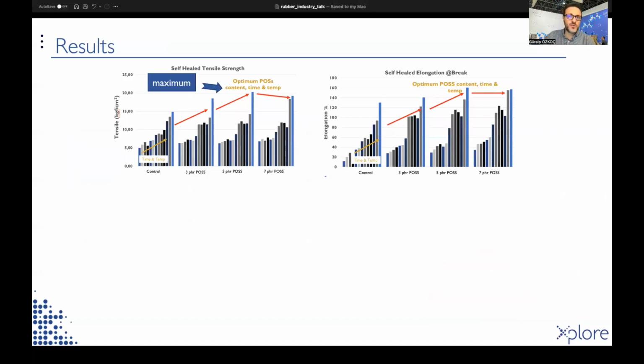In these 2 figures on top, you can see the self-healed tensile properties of brominated butyl rubber samples with respect to temperature and time. As you see, increasing time and temperature increase the healing properties of brominated rubber in any conditions. As the POSS content increased, the healing properties also increased. We observed a maximum at 5 PHR POSS for both elongation and strength.